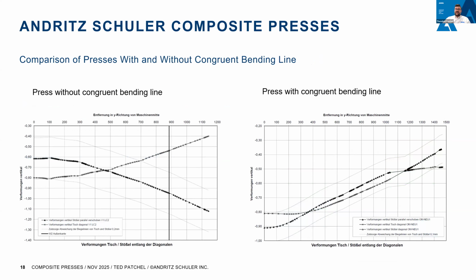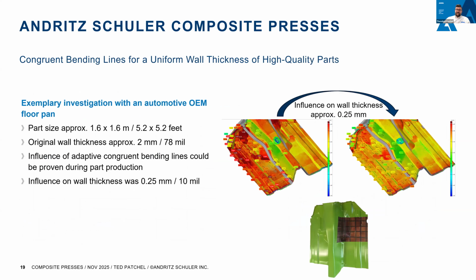In these graphs, you can see that the displacement against nominal becomes significantly skewed the further out you get from center without using the congruent bending lines. With the congruent bending lines, you see that your finished part ends up much more in line with the desired outcomes. We did a case study regarding these congruent bending lines with an automotive OEM's floor pan, and we were able to modify the original wall thickness that was 2 millimeters by 0.25 millimeters, which was able to achieve a greater lightweighting without any reduction in parts lost due to tolerances. This study also proved that this technology can be adapted and used for part production.